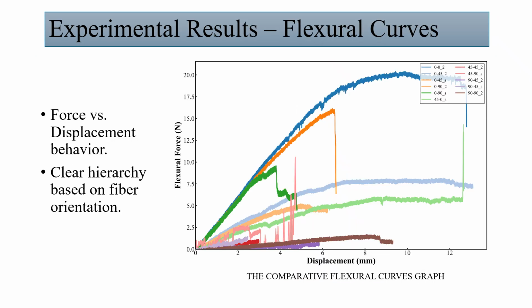This graph illustrates the raw force displacement response for all layups. As expected, fiber orientation dictated the mechanical performance. The stiffest curves, reaching the highest forces but breaking on minimal deflection, represent the 0-degree dominated laminate. Conversely, the layups that stretched far to the right, showing massive deformation before failure, are the off-axis 45 degrees configurations. Finally, the 90-degree laminates failed almost immediately near the bottom of the graph.